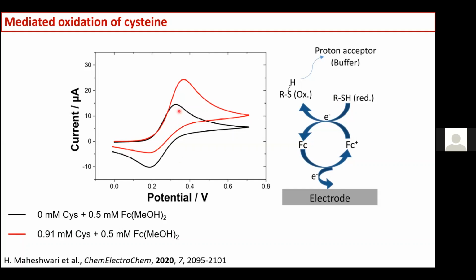The cyclic voltammogram of ferrocene in the absence of cysteine at a bare electrode, and here after the addition of nearly 1 millimolar of cysteine, and you can see that you have an increase of the signal of the forward peak, which corresponds to the regeneration of ferrocenium into ferrocene by the cysteine. And then you can see that the reverse peak is diminishing because there is very little reduction of ferrocenium as it has been consumed by the cysteine.